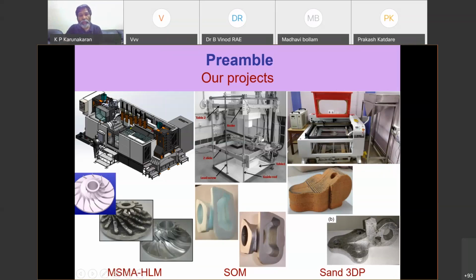Another way of doing 5-axis cladding, which I have not shown in this figure, is that now you look at this particular impeller. If you forget the blade, it is a simple geometry converging upward. That means it does not require any support structure. So we built that hub or the inner geometry using a 3-axis cladding system in the usual way of additive manufacturing. Then we use the welding gun to put the beads in 5-axis.